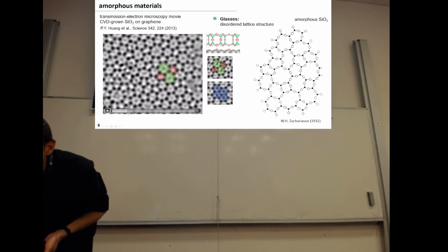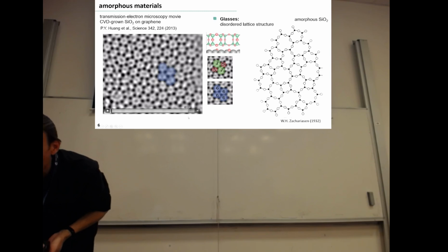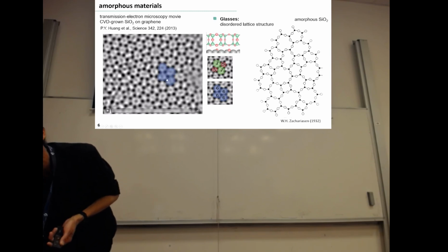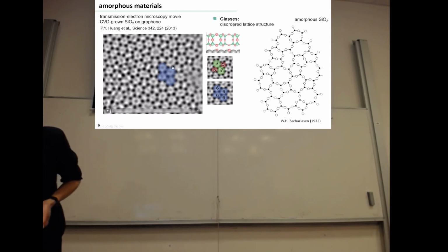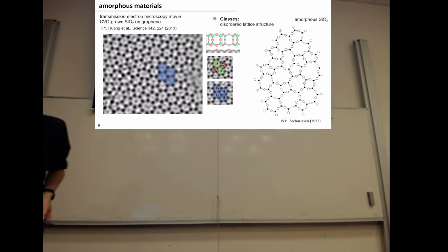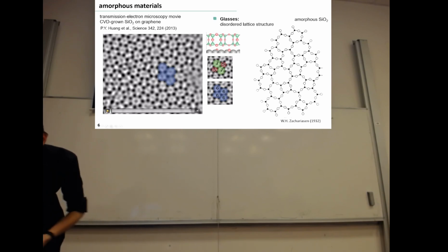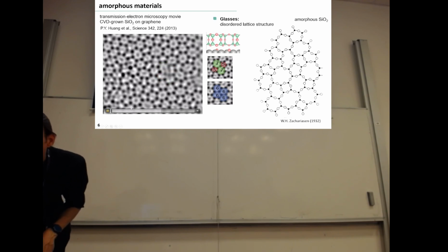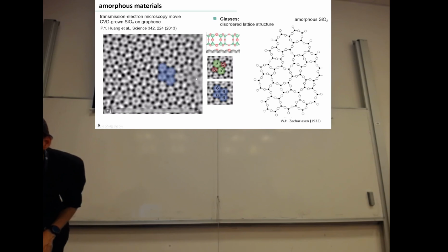Now if you let time evolve, suddenly something occurs and there's some rotation between the atoms happening. Now you have this more crystalline version of the material in this small space here. So the material crystallizes a little bit just by providing some noise or some tunneling. And there's a lot of this going on here too.